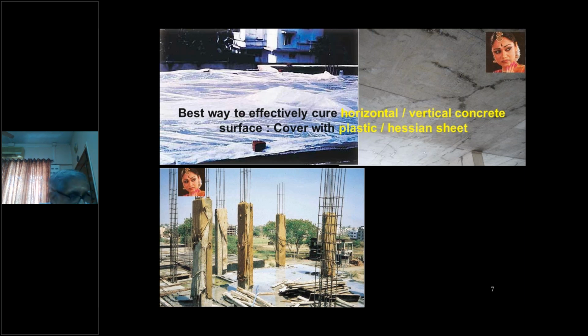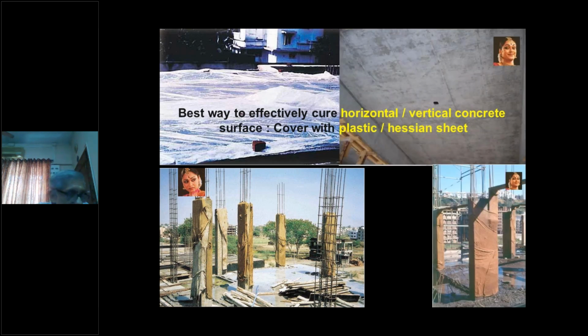The next slab we cast in our presence, putting the plastic sheet, and you can see how beautifully it has come. Not a single crack. You will be searching for the crack. Even the vertical curing should be done with a proper cover of Hessian cloth. If you are lazy to do proper curing of vertical surfaces, maintain the formwork for some time. Mind you, it should be a wooden formwork and not steel formwork. Otherwise, that will generate heat and you may get cracks due to that also.